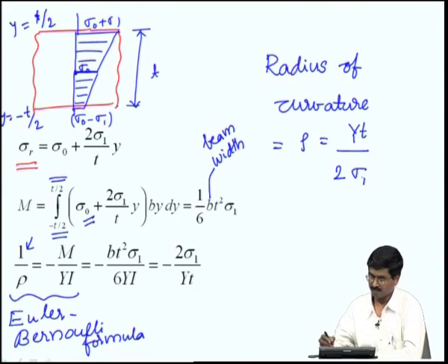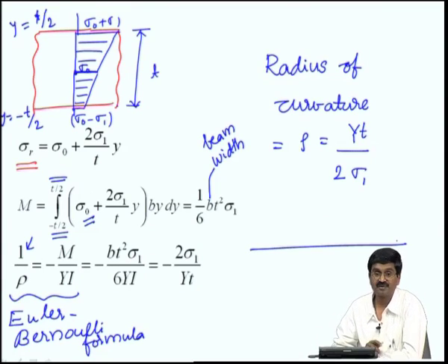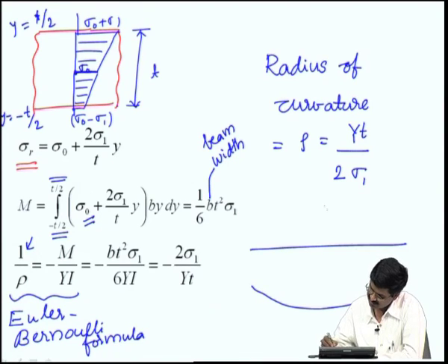Okay. The more the residual stress gradient, the smaller the radius of curvature. Where radius of curvature is small, that means that it bends more. Note that if there is a straight line, its radius of curvature is infinity, that means that there is no curvature, no bending. Whereas this one has a certain radius of curvature, so it has bent a little bit.